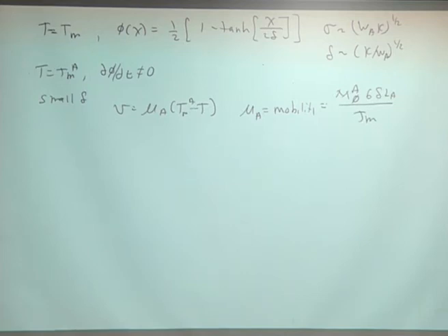That should be there. But I think what's quite clear is that now in your phase field model, you'll have these interfaces moving at some velocity v, and as long as M is non-zero, M is not infinity, you'll have some sort of deviations in the temperature, right? And so you'll never get this. So in other words, the solid won't grow at the equilibrium melting point. It'll grow at some below melting point associated with the mobility. So that's kind of an issue, but it's embedded in the phase transformation problem.